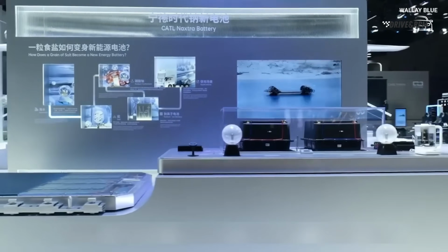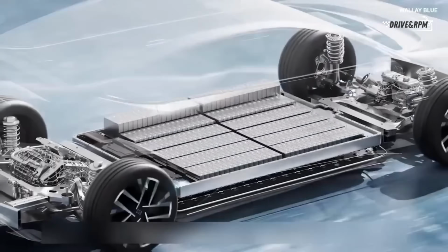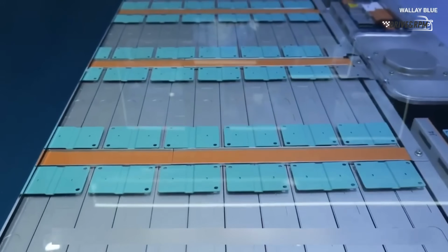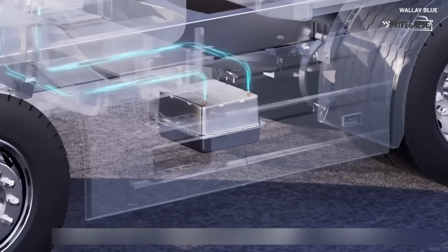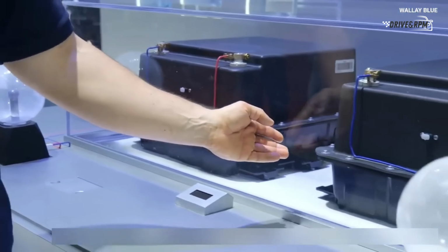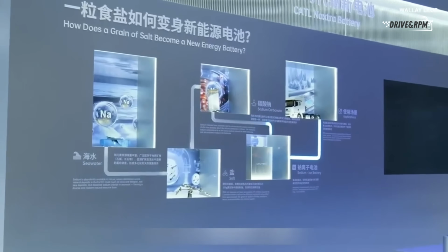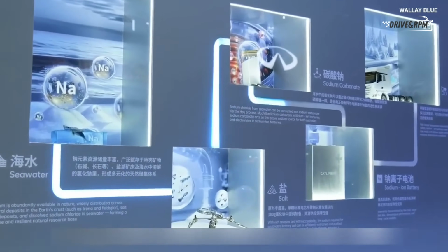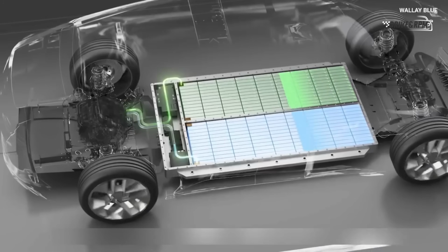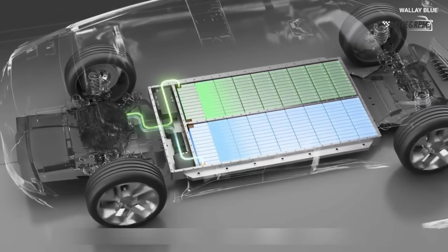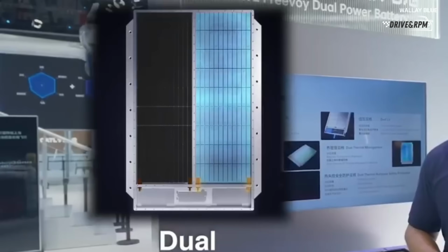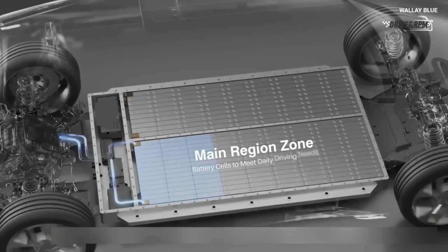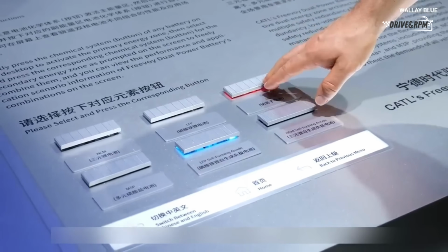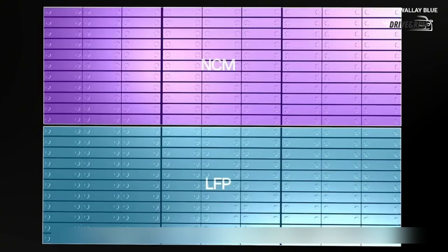By stabilizing this cathode structure at the microscopic level to prevent transition metal dissolution, CATL successfully pushed the gravimetric energy density of these commercial cells up to 160 watt-hours per kilogram. Let's put that number into perspective. 160 watt-hours per kilogram completely closes the gap with the first generation of standard lithium iron phosphate or LFP cells that currently power millions of standard-range EVs worldwide. And CATL has already confirmed that their next iteration is validating at 200 watt-hours per kilogram. They have effectively solved the physics problem of gravimetric density. But as any engineer knows, energy density on a test bench is useless if the battery fails in the real world, and the real world gets cold.